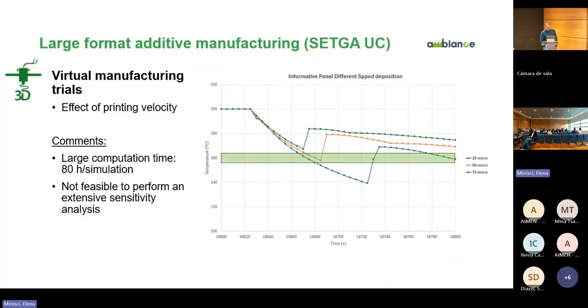So our base simulation would be the orange line. And if we go to a quicker simulation, a quicker impression, we get higher temperatures on the substrate. If we go at a lower velocity, we have very low temperatures. In this case, for the material we are using, AIMEN determined a processing window that recommends having this substrate temperature in a certain range, around 160 degrees. So we can analyze by simulation what would be the velocity required to be in this range.